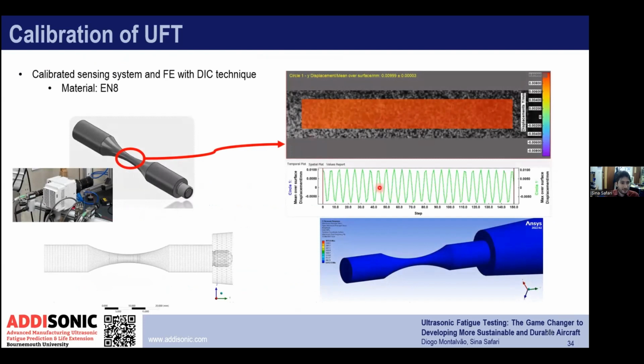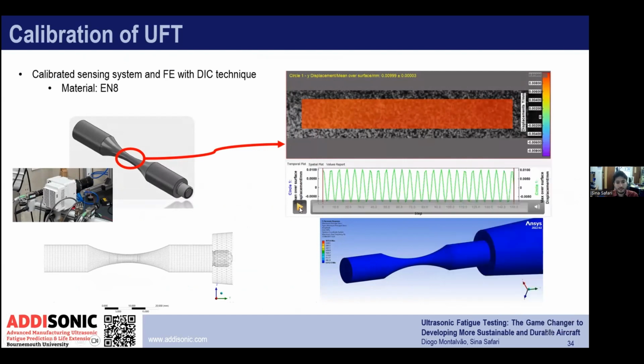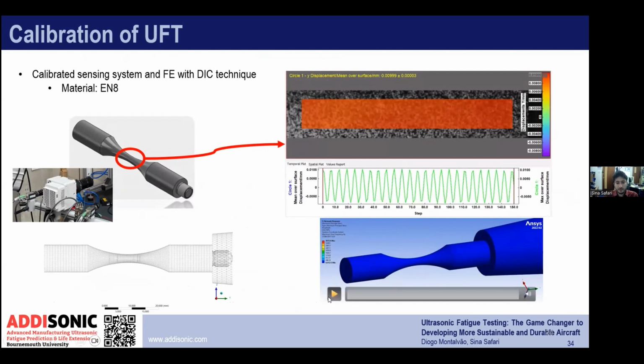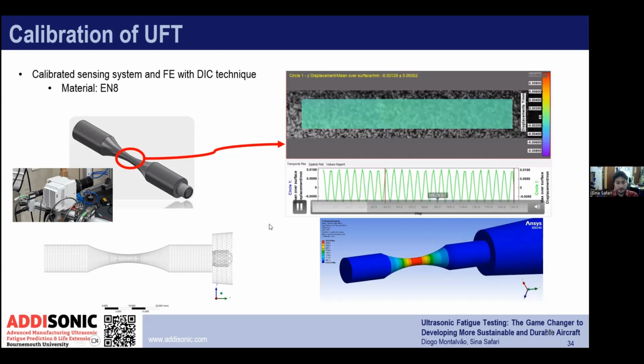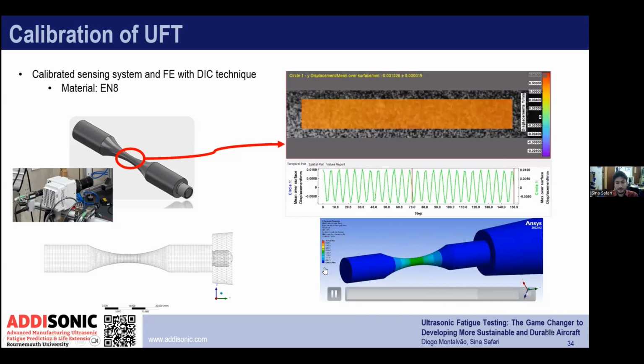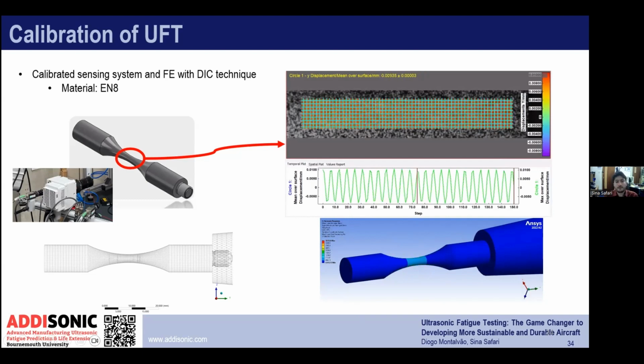Thank you. So this slide shows exactly how we measure the strain in the middle section of the specimen using the DIC system. If we play that and also play the one in the bottom, as you can see, we have the simulation of vibration, and that shows the stress, or strain, in the middle. Both of them are similar. We can, because it's in the linear regime.